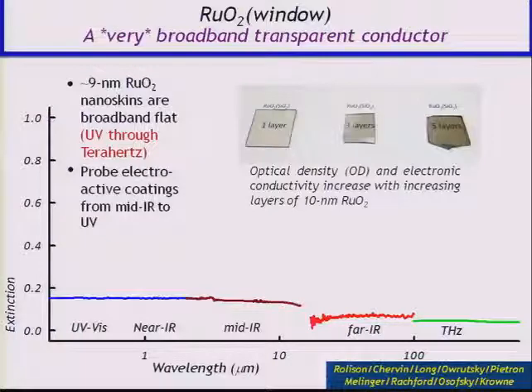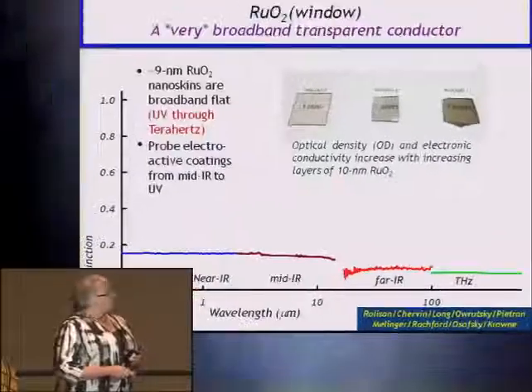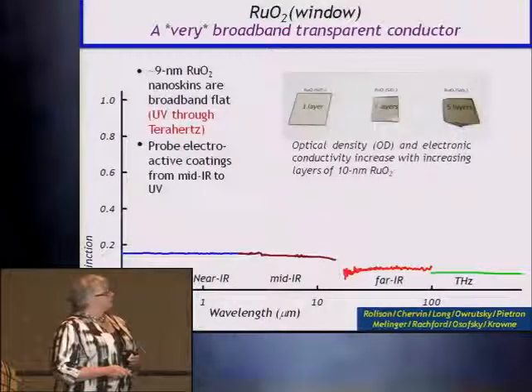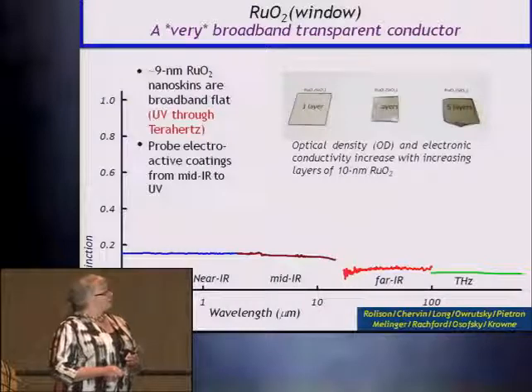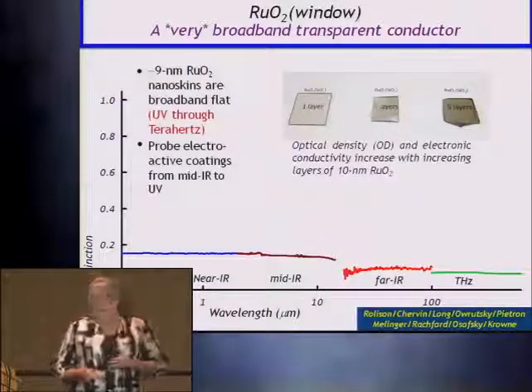But while we've got ruthenia on planes, let's put it on a transparent window. And we can also repeat these deposition procedures, so we can put down 1 layer, 2 layers, 3 layers. So here's an example of 1 layer, now a nanoskin, not a nanoshell, on fused silica or quartz. You can see it darkens at 3 layers, but is still transparent. Darkens at 5, but you can still get some light through it.